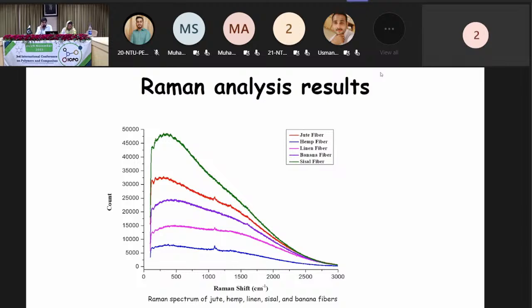Regarding the Raman analysis results, the major peak at 1096 is indicative of the C-O stretching mode of cellulose, but the peak at 380 is only associated with crystalline cellulose and is not present in amorphous cellulose.